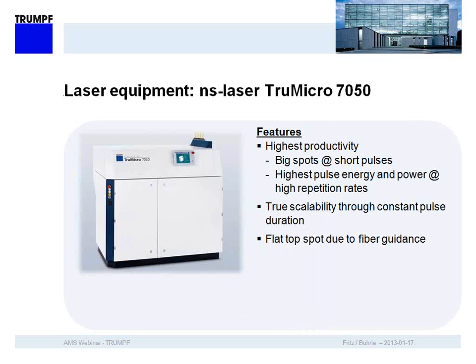For the laser source, we used our nanosecond laser from the TruMicro series, which is a very high productive laser source with high laser quality. That means we can use small fiber with small diameters, which helps us in terms of optical arrangement in the optic. So we could really play in different